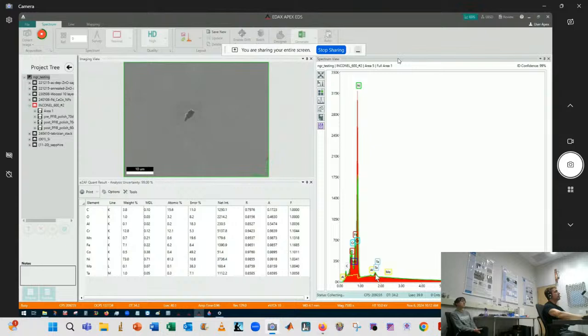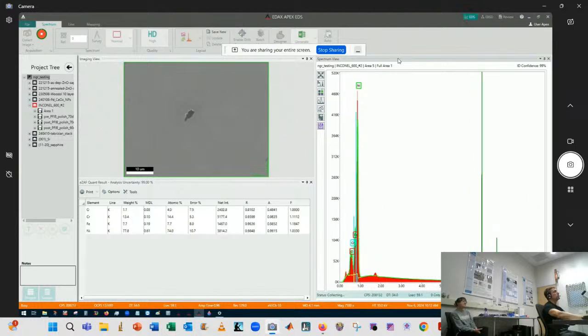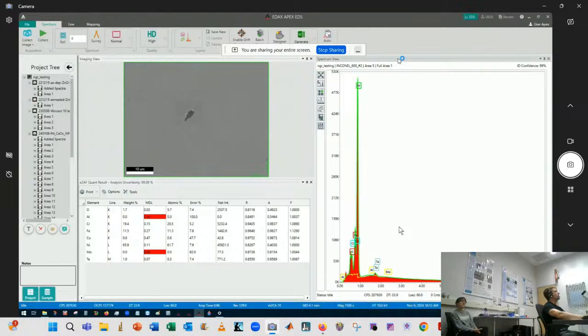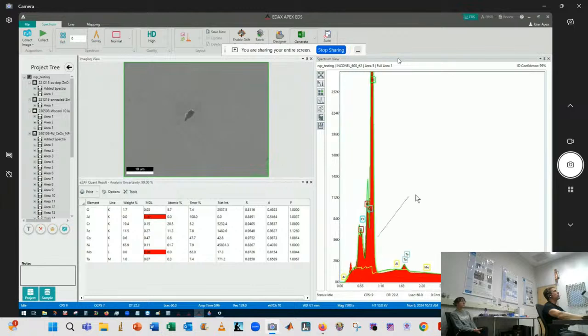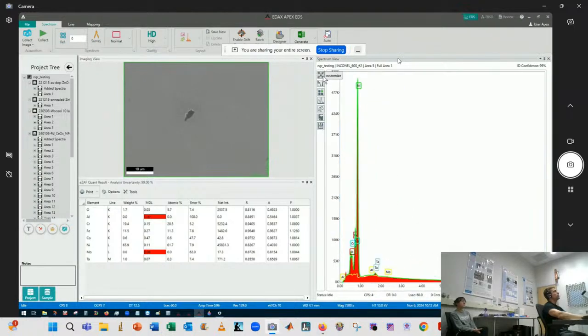I wonder if maybe this peak here that's being labeled as tantalum, that could be actually some peak of the nickel L right here, which is probably likely. I don't think there's tantalum in this. And then you've got a little bit of chromium and iron here. Get rid of manganese. I don't know, it's auto IDing it for some reason. Cobalt. Okay, so then we're all done. Go ahead and blank the beam. Okay, so that's our EDS result.